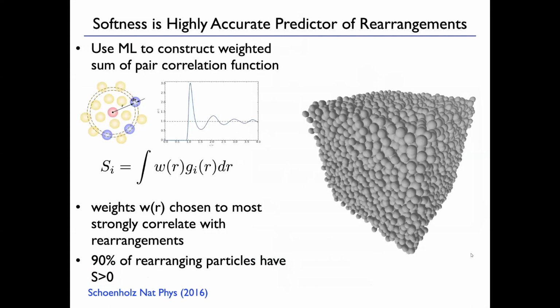All right. So what this amounts to, though, in the continuum limit is just that softness is this weighted integral of the local pair correlation function, where the weights have been chosen. The weights basically are the hyperplane, are related to the hyperplane, and they've been chosen so the softness correlates most strongly with rearrangements. And it works.